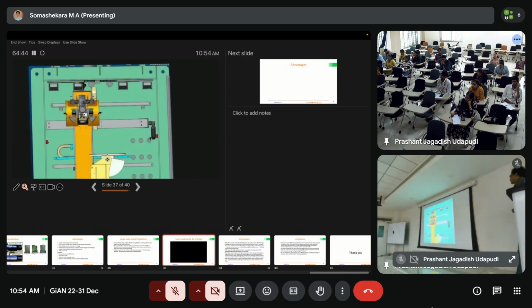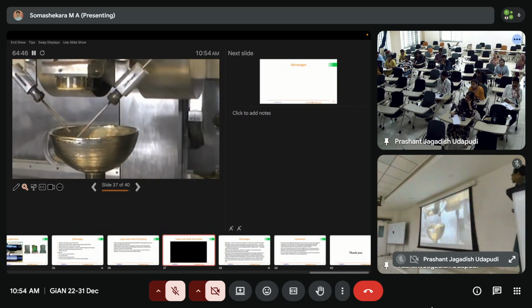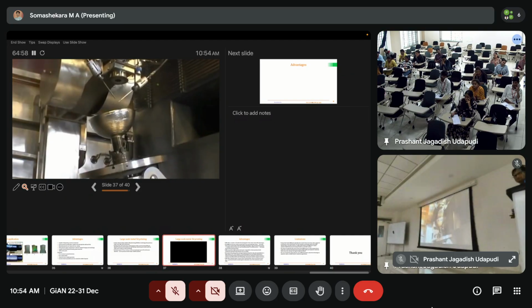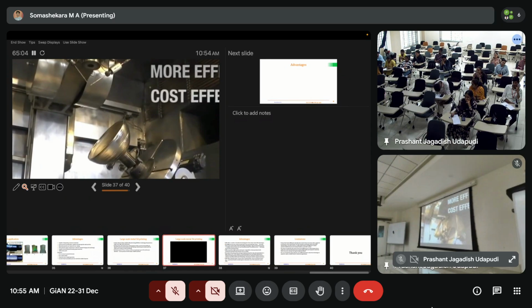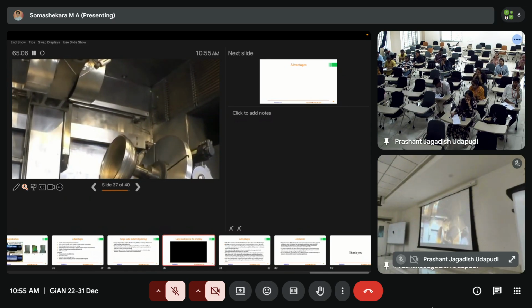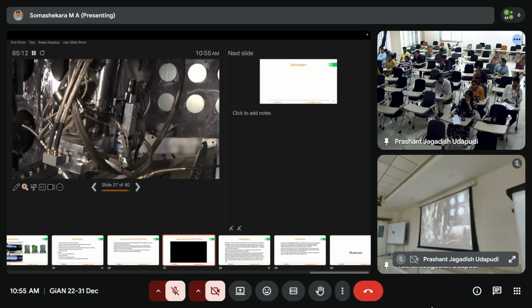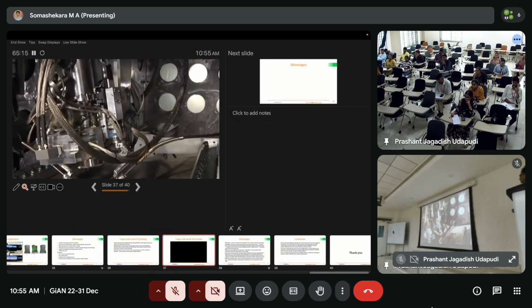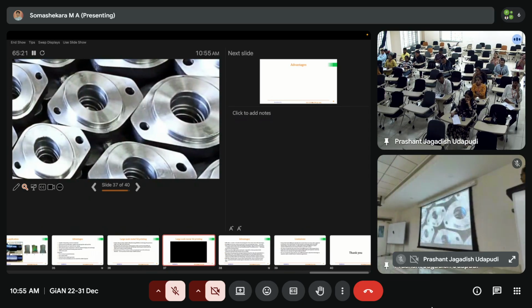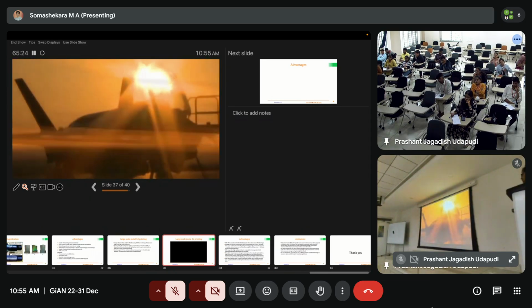Starting with a 3D model from a CAD program. This is the electron beam. A fully articulated moving electron beam gun deposits metal from wire feedstock layer by layer until the part reaches near net shape and is ready for finished machining. Deposition rates can range from 7 to 20 pounds of metal per hour, which is significantly more efficient and cost-effective than selective laser sintering processes that utilize messy powders. In addition, a dual wire feed system can be utilized with the EBAM process to increase deposition efficiency, as well as to easily switch to different deposition materials. So whether you need to produce a functional prototype or a run of production parts, the possibilities are virtually endless.